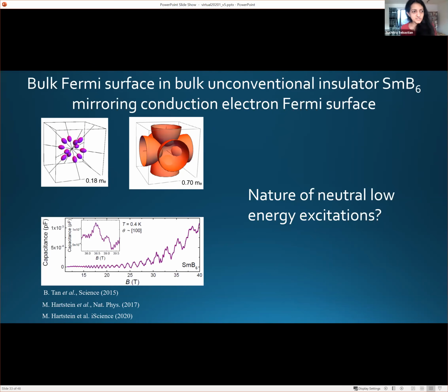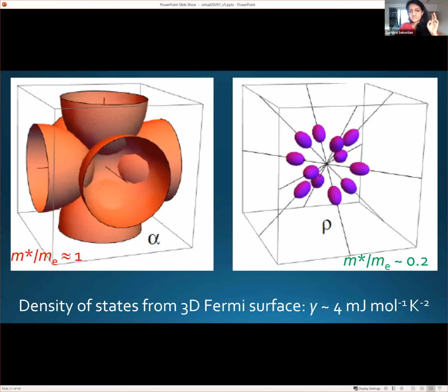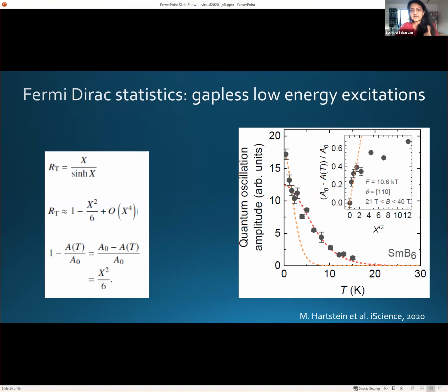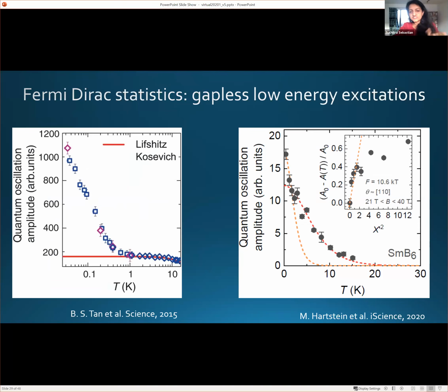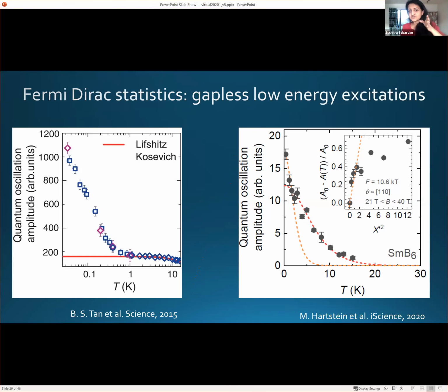That's a very good question. Of course, this is not an immediate assumption. So the reason I say we see a Fermi surface from our own measurements, this is the difference between gapped and gapless, and I completely agree that this is an important distinction to make. Just from quantum oscillations, it could come from a gapless model, which would not imply a Fermi surface. So from our measurements, from the fact that the quantum oscillation amplitude keeps increasing down to the lowest temperatures, down to millikelvin temperature, which is much smaller than the gap energy size, that's one of the indications we use.